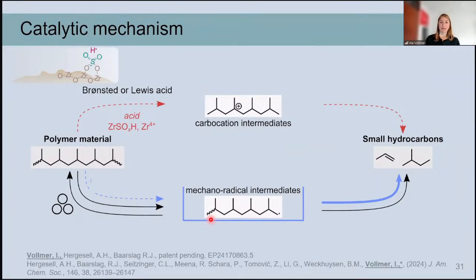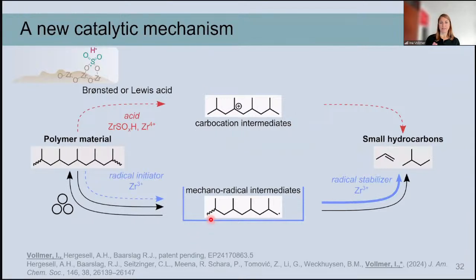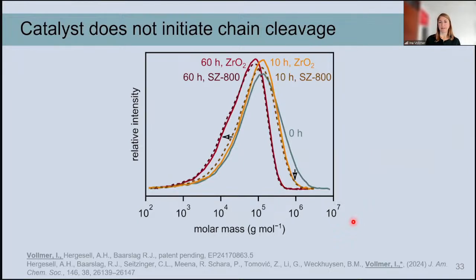And then we further tested whether it is indeed the radical initiation, or whether the radicals are somehow stabilized and this formation of smaller hydrocarbons is promoted. And so for that, we looked at the GPC curves. So this is the molecular weight distribution before the milling. So this is in grey without any milling. And then we milled for 10 hours and for 60 hours. And you can see the solid lines are without the catalyst, and the dashed lines are with the catalyst.